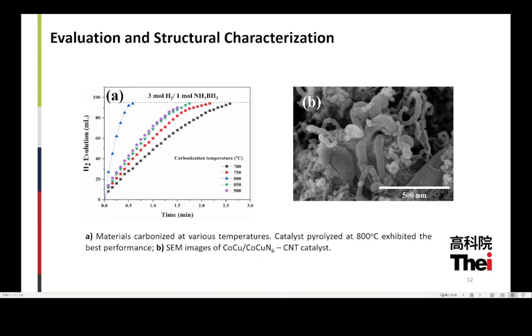In this slide, graph A shows our best performance is with the cobalt-copper catalyst made under 800 degrees Celsius of carbonization. Also, on the right-hand side, graph B shows the best catalyst, as I said, exhibits a convoluted worm-like structure and shows a successful formation.